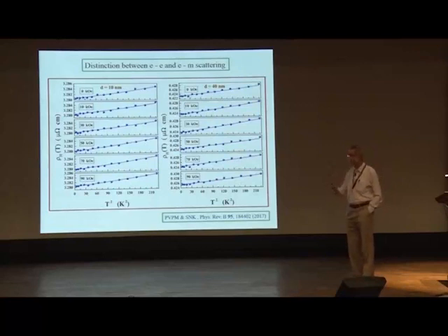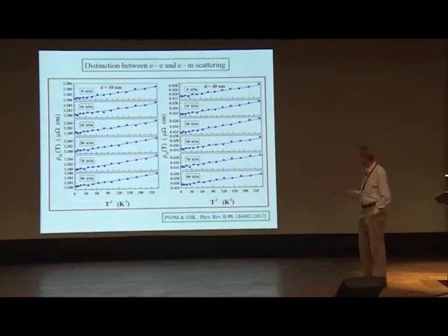So you have fewer magnons at high fields to scatter electrons. Okay? So that means the electron-magnon scattering will get suppressed quickly when you apply the magnetic field, whereas electron-electron scattering would not get affected at all. So what you see here is basically that the coefficient of the T-square term is nothing but the slope of these curves, and you find that that slope does not change with field.